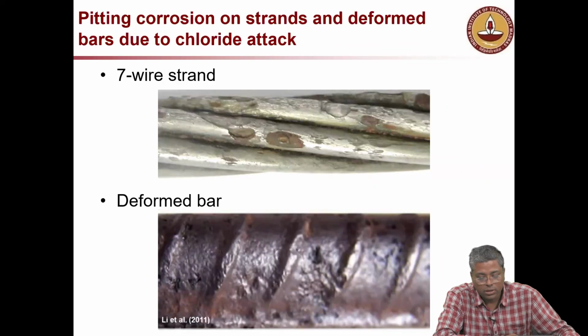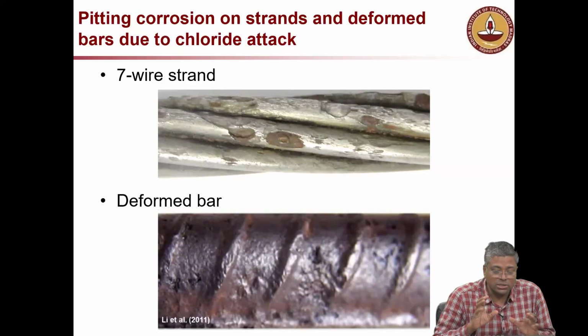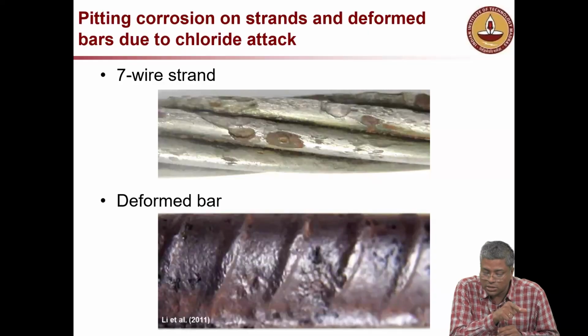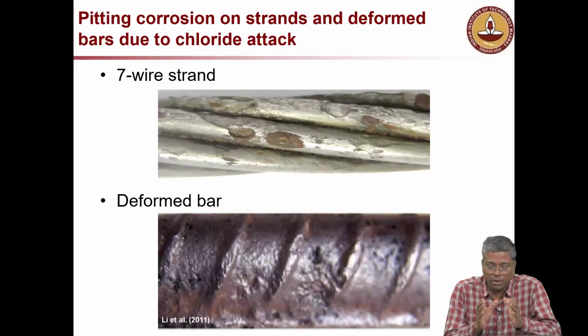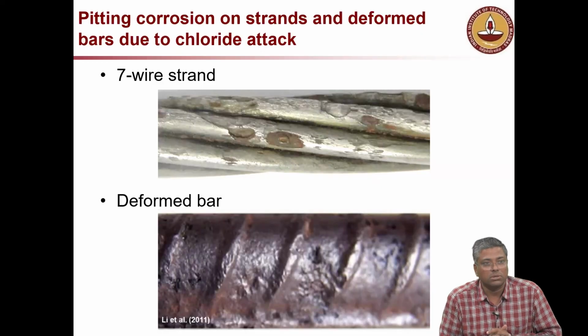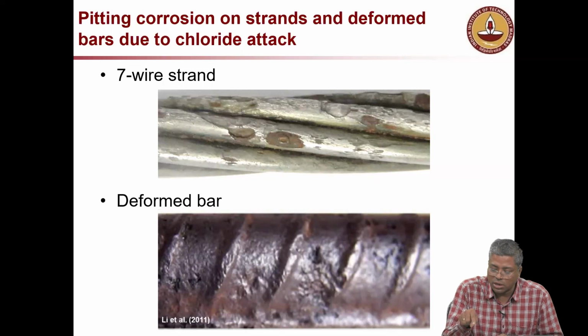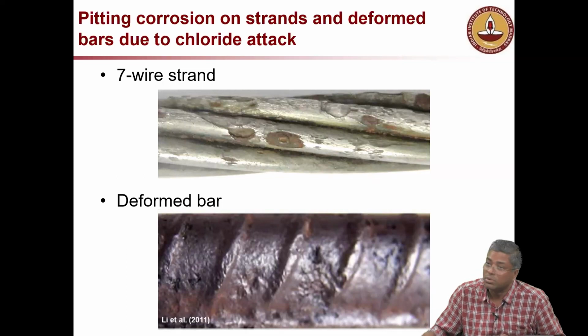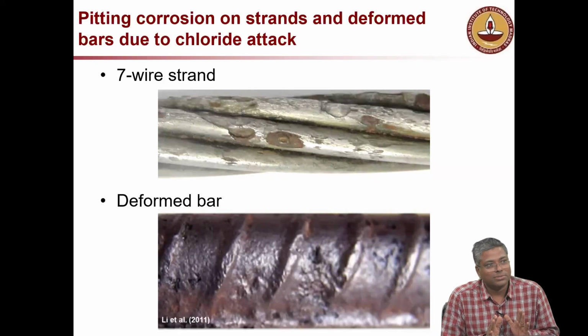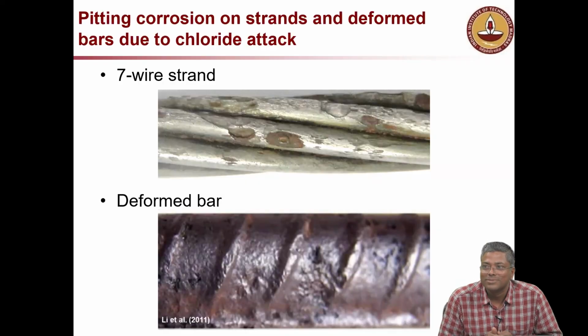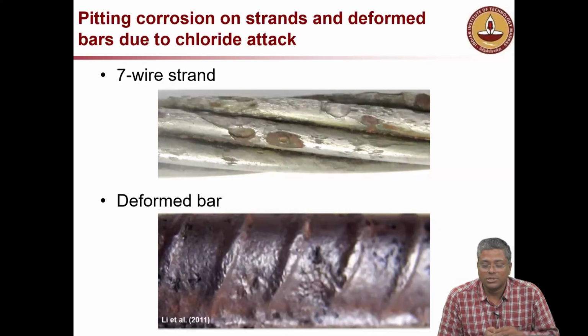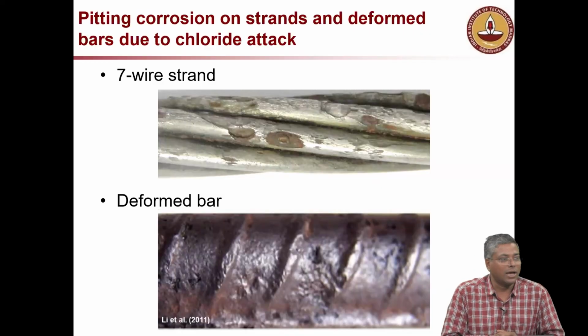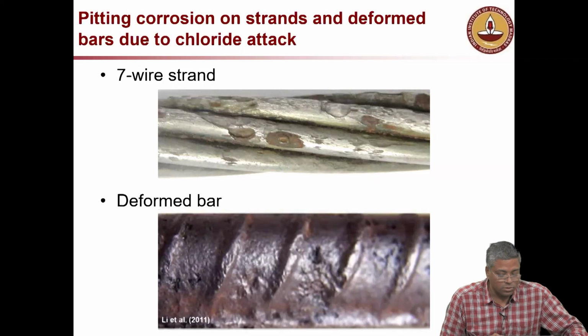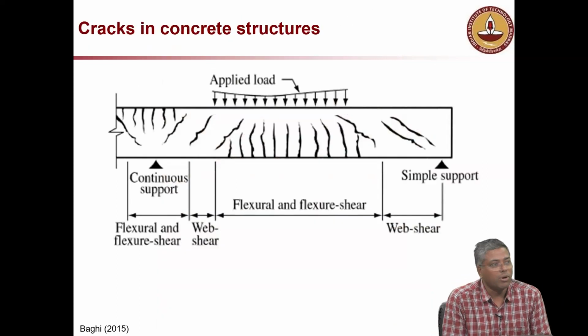Okay, the pit keeps growing. At the bottom one also you can see some locations with a lot of corrosion, some locations without any corrosion. On the strand it is very clear. There is a pit, and there are other locations with absolutely no corrosion. You can see in the strand photo, bottom right of that photo, you don't have any corrosion. Bottom right. So same strand, in the same concrete. Okay. So what type of corrosion is this? Micro cell, macro cell, what would you call it? Strands, usually you put in high quality concrete. This particular specimen is from a high resistivity concrete. Okay. So micro cell. Now cracks, also a big problem.